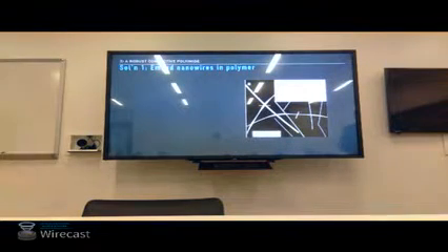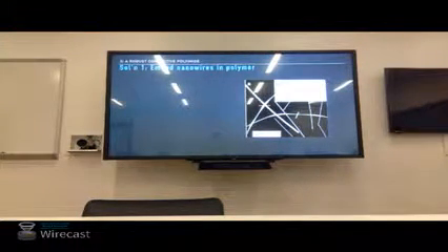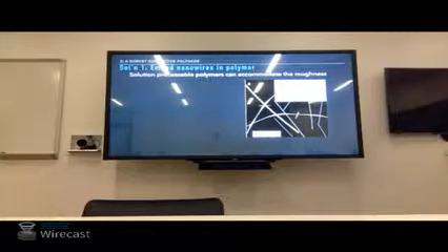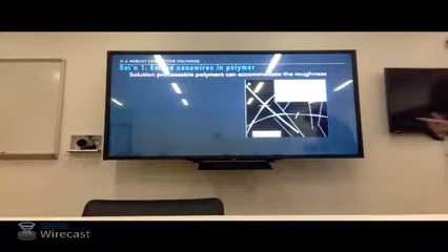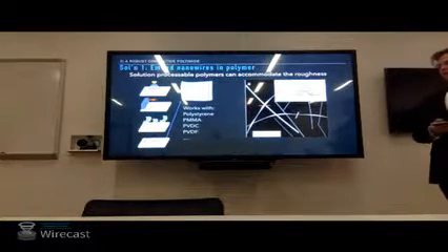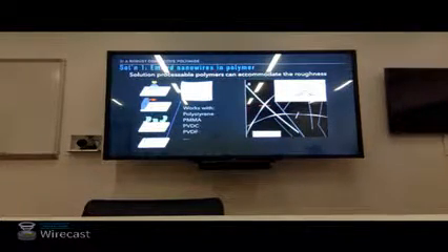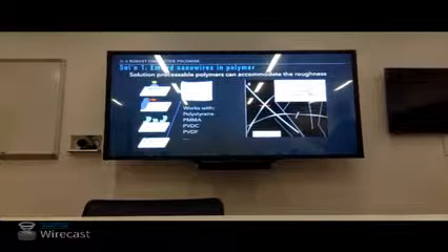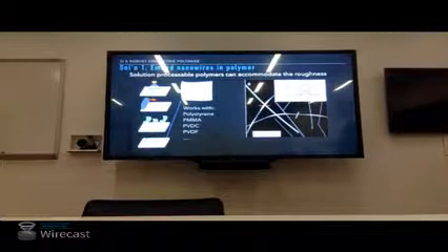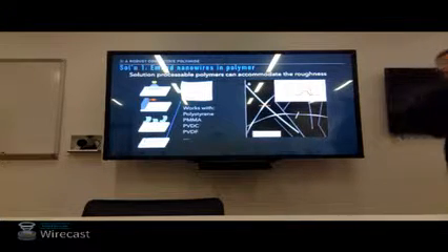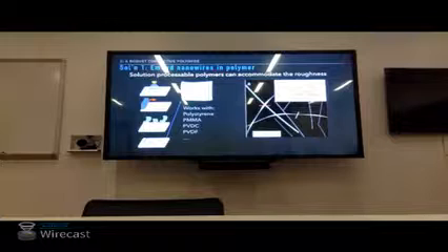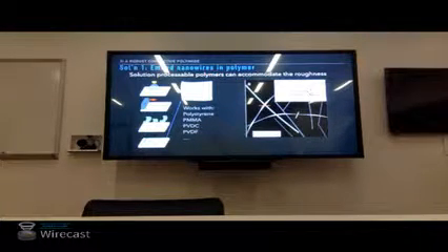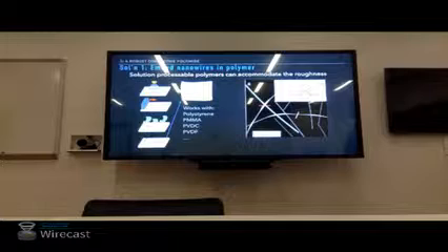Luckily, there's a common solution to this problem in the literature, a solution that we're going to employ, which is to embed the nanowires in a polymer layer. Solution processable polymers can accommodate this roughness. Now, it's important to be in solution phase when we process because we want the polymer to kind of encapsulate all this roughness. The process kind of looks as follows. We'll make a silver nanowire network on a rigid substrate, say glass, a wonderful material. Then we'll encapsulate with a polymer. It says colorless polyimide there, but it works with a whole range of polymers, polystyrene, acrylics, PVDC, saran wrap, PVDF.